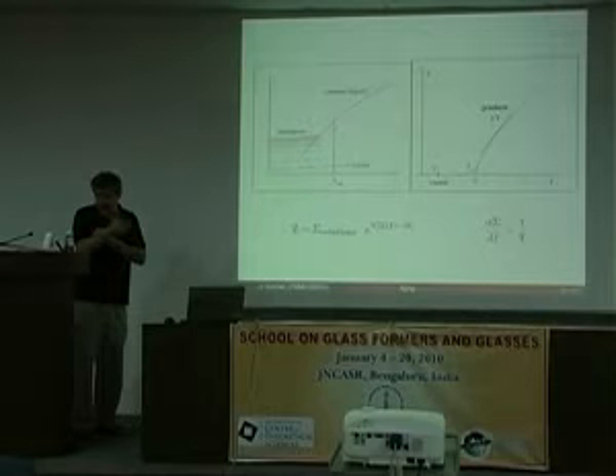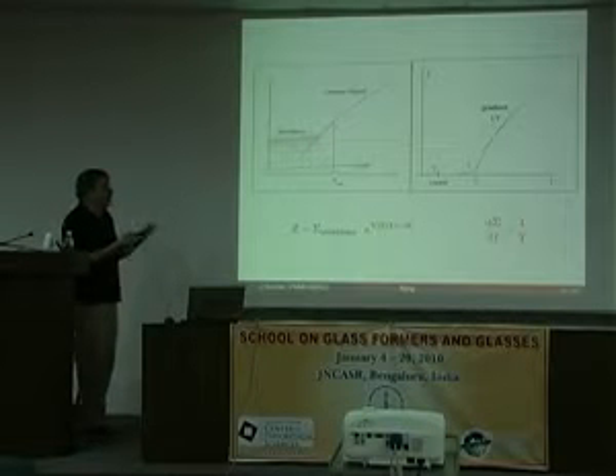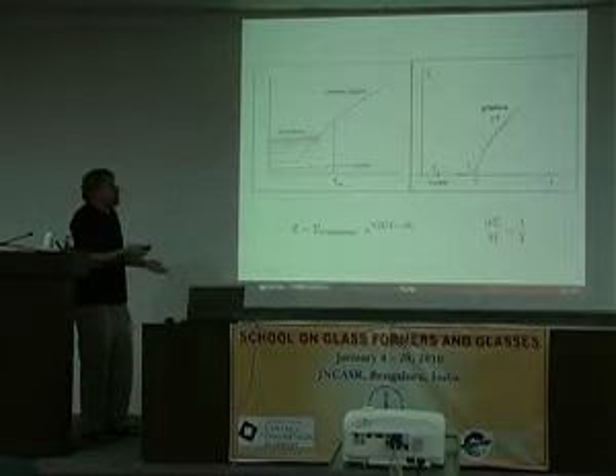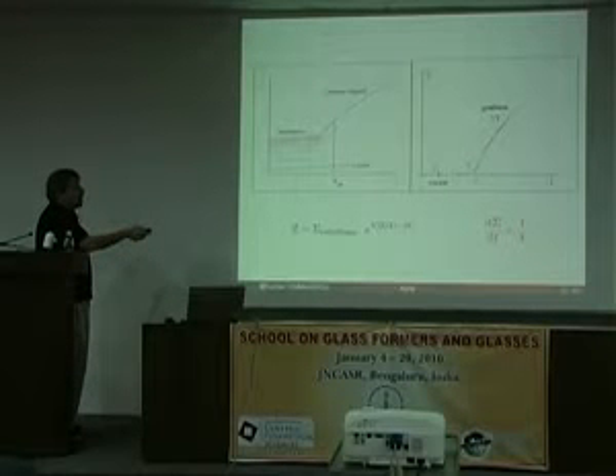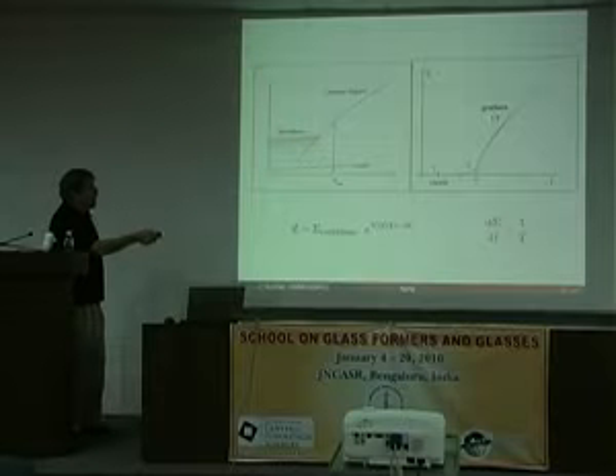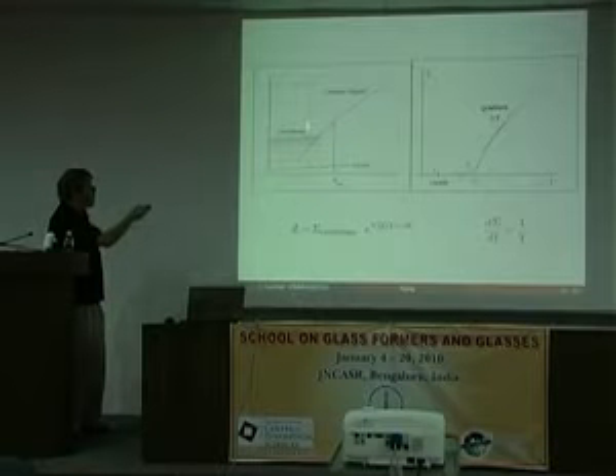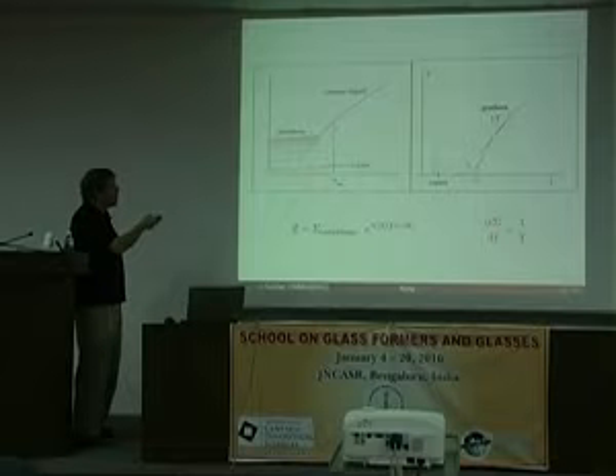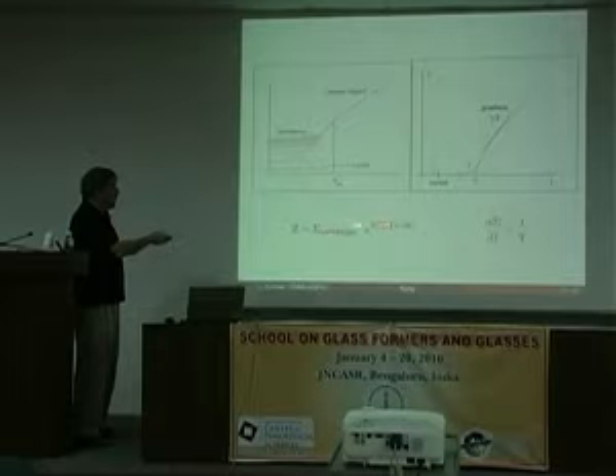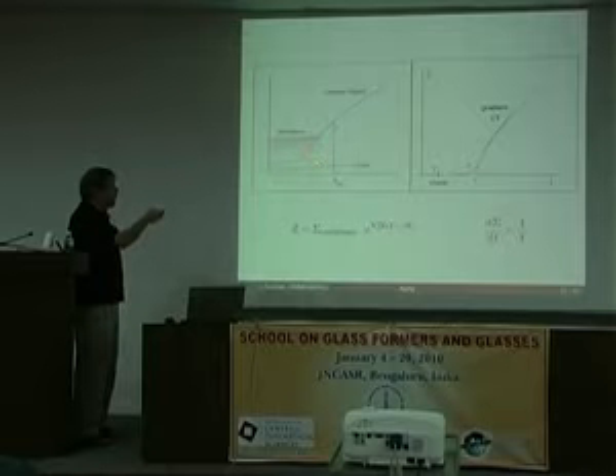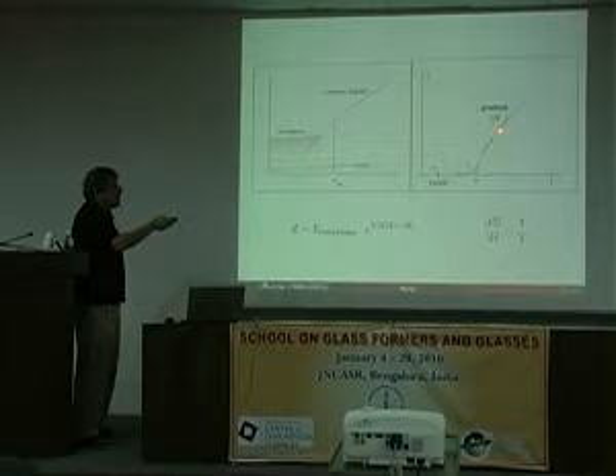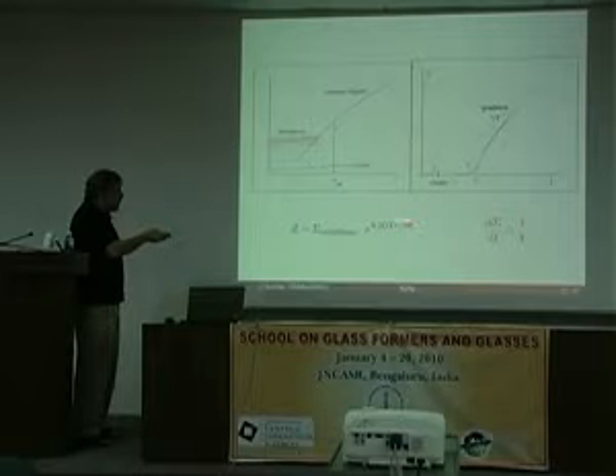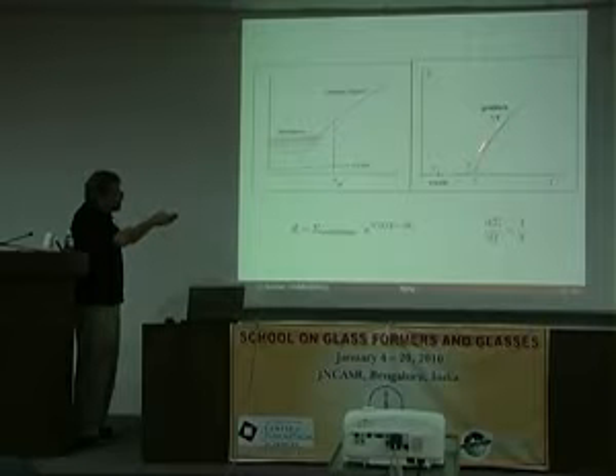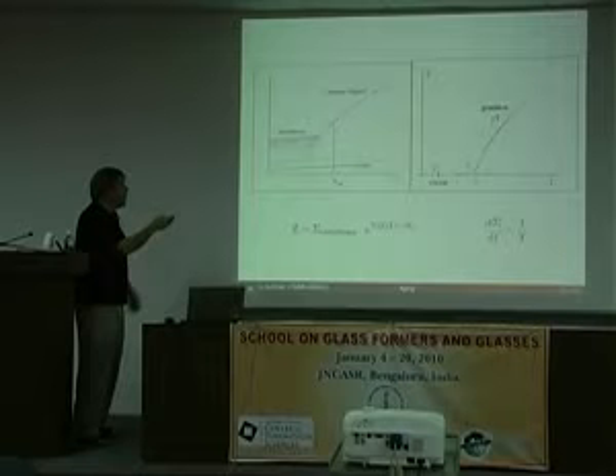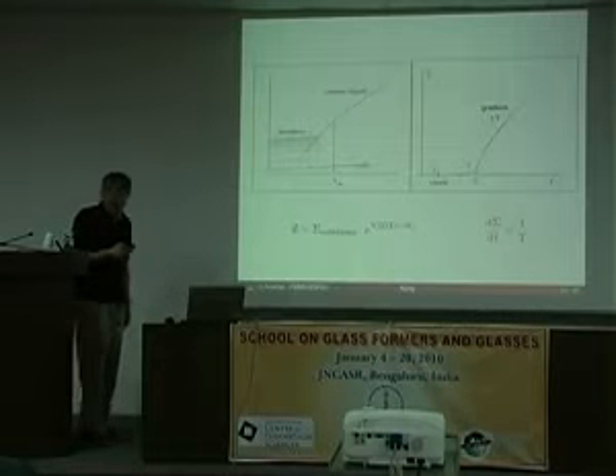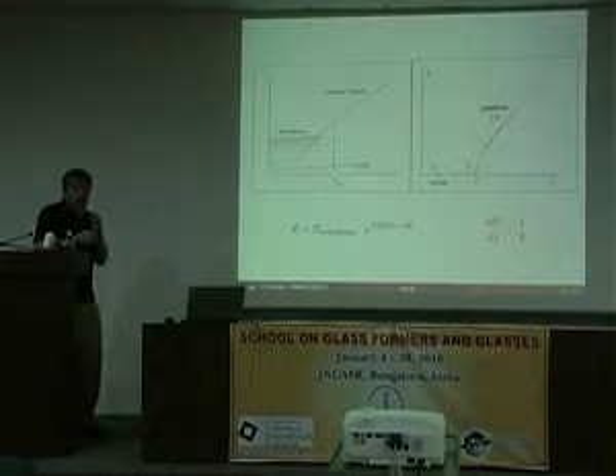The solutions to this, mainly by Chandan Dasgupta and collaborators, are what you can do with a computer these days, but you cannot do miracles. And the liquid solution, I said, is represented both by this line and by this multitude of solutions, because if you do the Gibbs ensemble and write it as a Gibbs sum of all these solutions, which is a way of refinding equilibrium, your equilibrium happens in the saddle point of this equation, which is exactly where the gradient of this curve, which represents the log of the number of these solutions, is exactly 1 over T. This is the equilibrium. So this is a very crash course on random first-order theory.